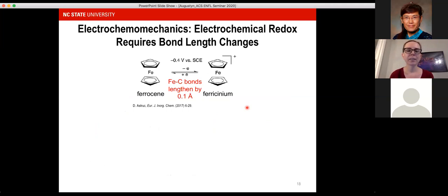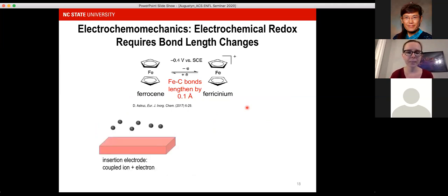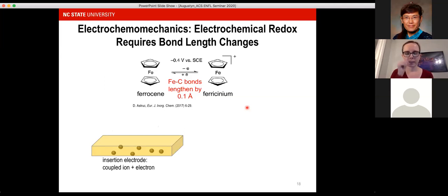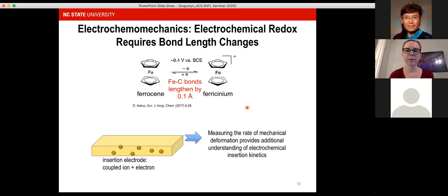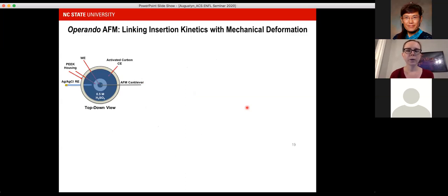And this is kind of an aside to say that anytime you have an electrochemical charge transfer event, you're going to have bond length changes. So even something simple as ferrocene being oxidized to ferrocenium, there's a lengthening of the iron-carbon bonds. You can use that as a feature of a charge transfer event taking place. The same is true in an insertion electrode. You have these coupled ion and electron processes. Typically, the materials will expand. Sometimes they contract. Very, very rarely do they not experience a volume change at all. And so if you can measure the rate of that mechanical deformation, that can give you additional understanding of electrochemical kinetics. So we did operando AFM at Oak Ridge National Lab with Nina Balke's team.